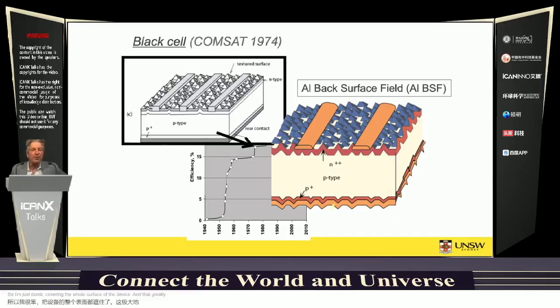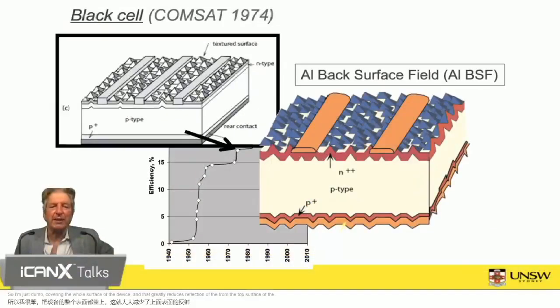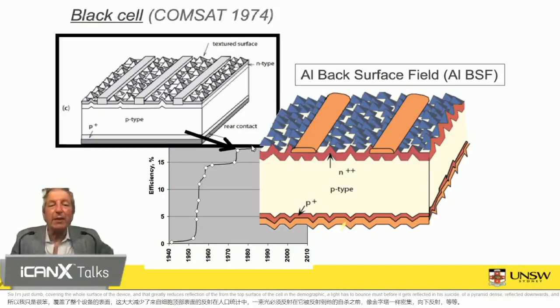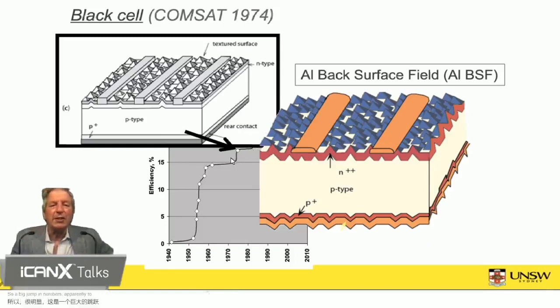And that greatly reduces reflection from the top surface of the cell, in that light has two bounces before it gets reflected. It hits the side of a pyramid, then it's reflected downwards and so on. So a big jump in efficiency to 16 to 17% type efficiencies was demonstrated by these black cells. And that structure became very important because with a slight modification, using a screen printing approach to apply these metal contacts, like screen printing T-shirts, a simple approach to apply these contacts rather than the more complex technology used in space cells, able to produce a very rugged cell structure that replicated very similar efficiencies.